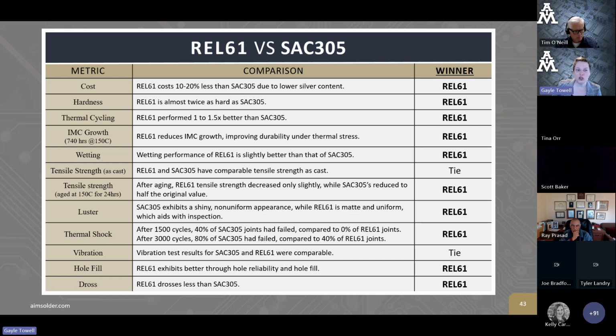It has that dull sheen, which again, people unfamiliar with dull looking alloys might be frightened by at first, but that's just the nature of this particular alloy, and it actually works in its favor when it comes to inspection. Thermal shock, it outperforms SAC305. Vibration test, the results were somewhat similar on that. Hole fill, it outperforms SAC305, and with dross, it drosses less than SAC305.